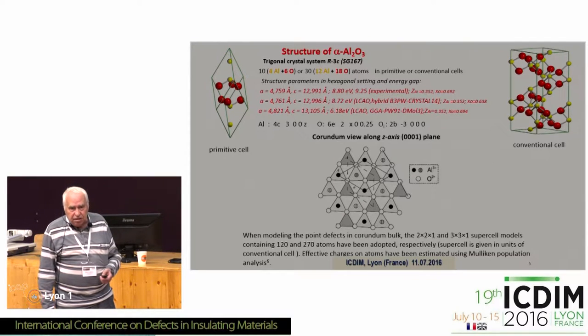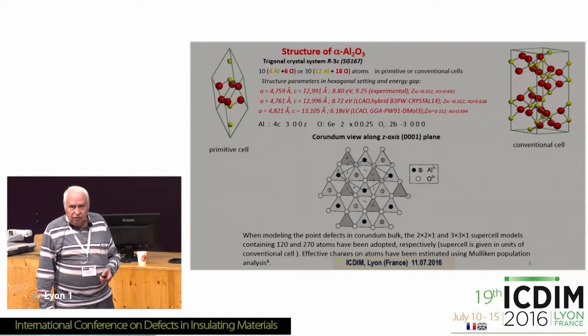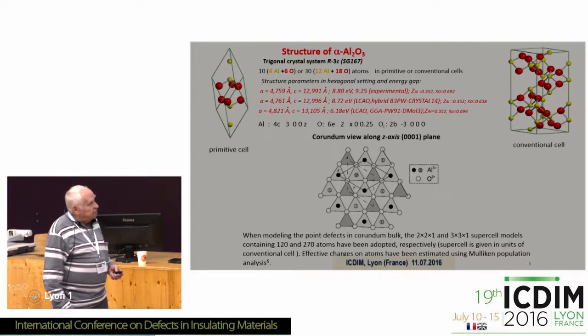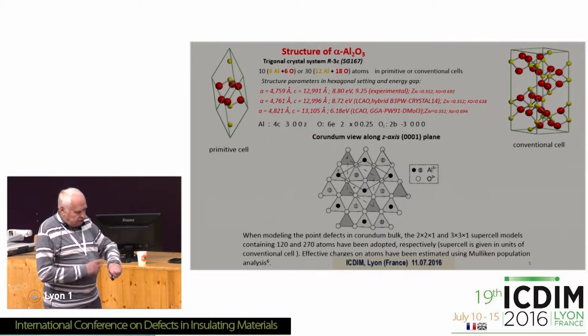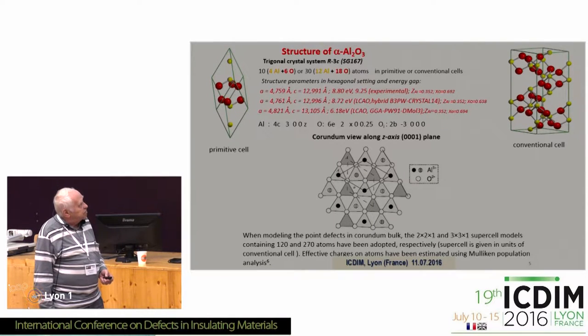The Corundum structure is shown here: on the left is the primitive unit cell — a rhombohedral lattice — and on the right, the conventional unit cell, which crystallographers prefer and which is three times larger than the primitive cell. The first and most important step was to reproduce the experimental structural data correctly. Corundum structure is described by four parameters: two lattice parameters and two atomic position parameters. The comparison with experimental data is shown, and the band gap is also reproduced correctly, close to 9 eV.